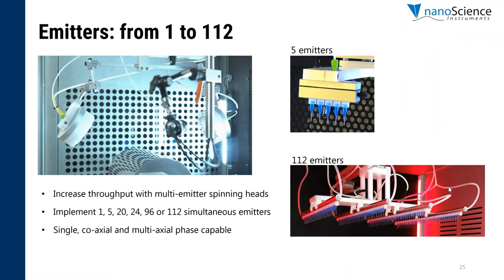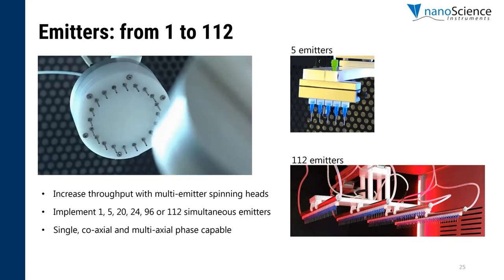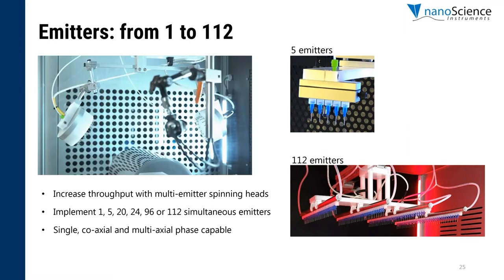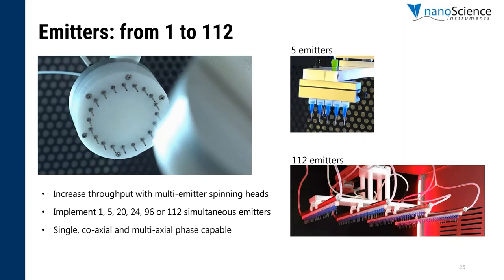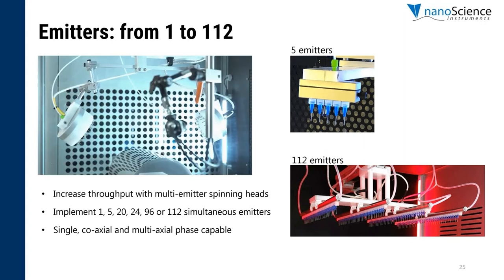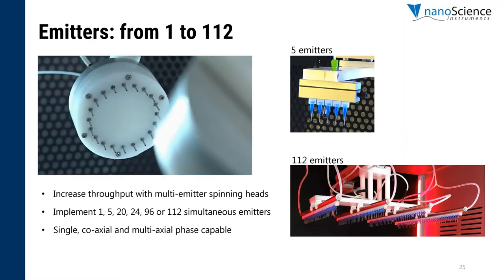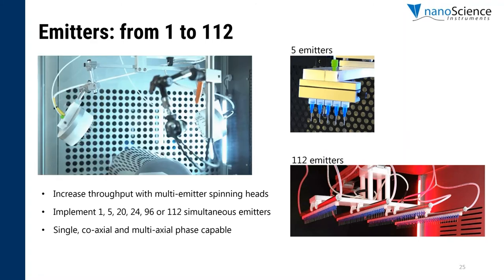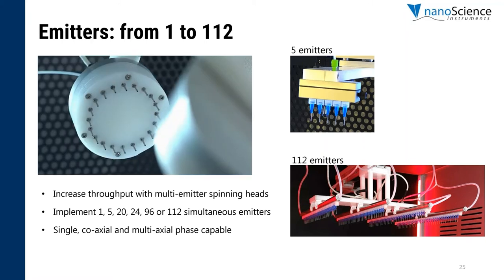The Fluidnatek technology operates through needle-based electrospinning and electrospraying, as I mentioned before. Depending on the Fluidnatek unit of interest, we can operate from 1 emitter to 5 to 10 and even all the way to 112 simultaneous emitters. So you can do either electrospraying or electrospinning processes with up to 112 emitters simultaneously. So this will allow you to increase the throughput by implementing what we call the multi-emitter spinning heads.